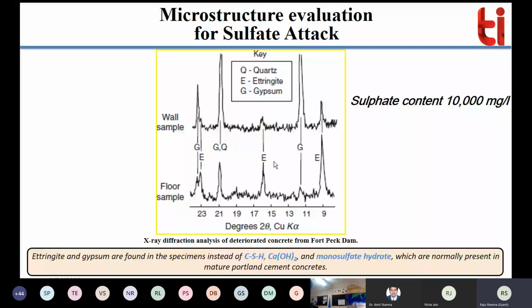But in this particular concrete sample, you found those particular minerals which are closely associated with sulfate attack, because of the sulfate ions, right? So it shows that your concrete is severely affected by the sulfate, and because of that, the degradation happened on this wall and on the floor. So this is one way you can correlate the microstructure testing evaluation with the large-scale failure of structures, right?